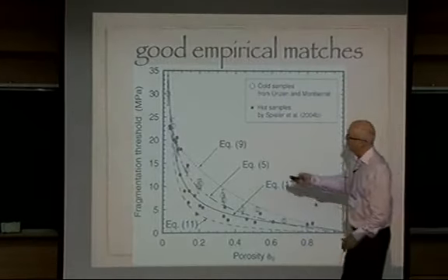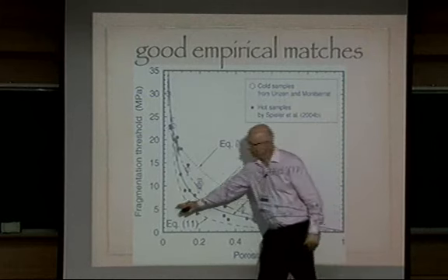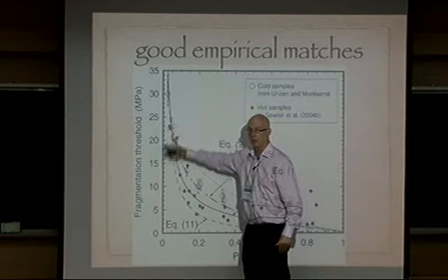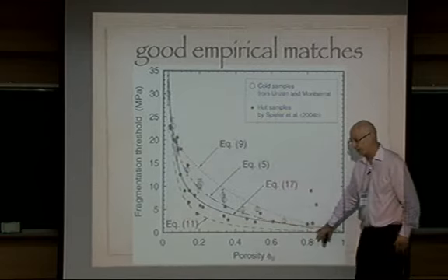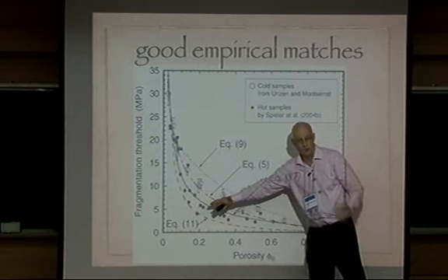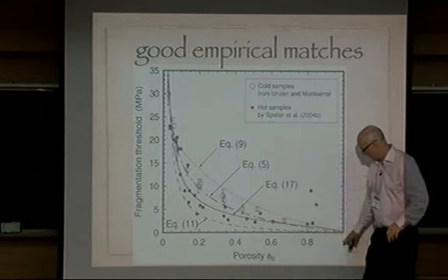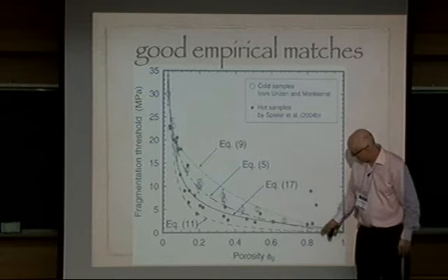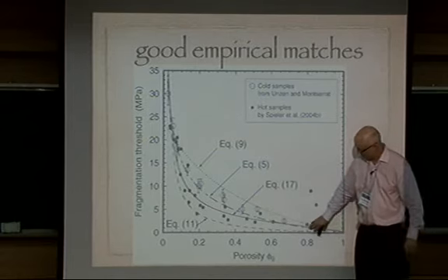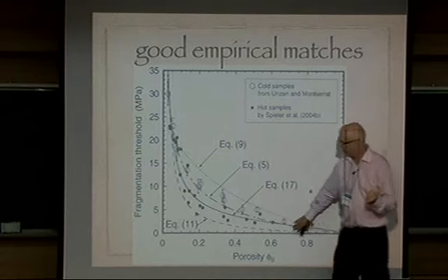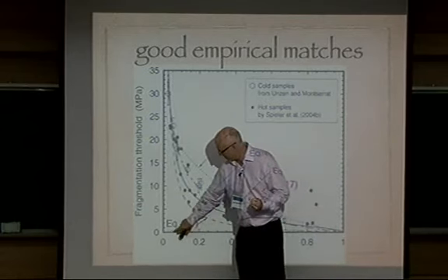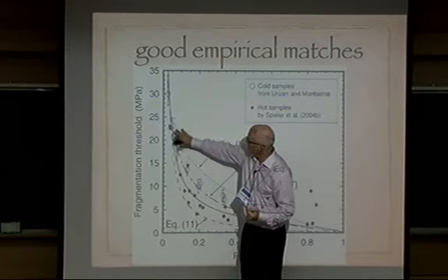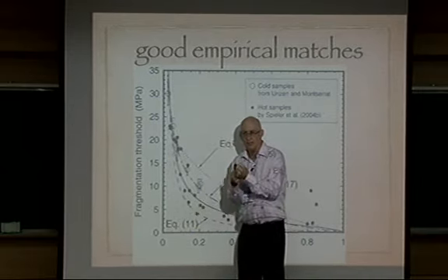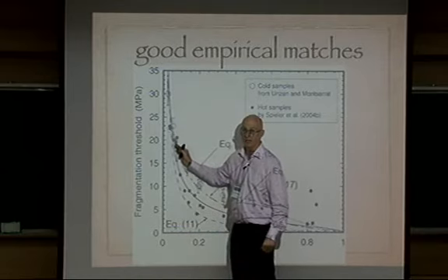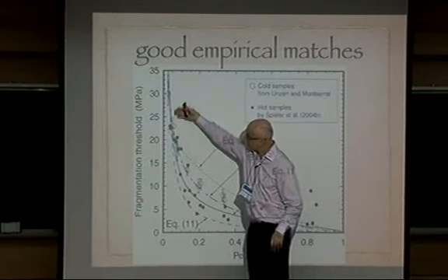They can produce graphs like this one here. The graph is fragmentation threshold: how much pressure do you need to break that rock, versus the porosity of the rock. How porous is the rock? From 0, no gaps, no gas inside it, to 1, nothing but gas. The dots are samples, anything up to 80% holes, right down to less than 10% holes. Of course, the fewer holes you have, the fewer spaces inside the rock, the harder it is to break it. There's hardly any gas in there, so it's hard to get enough gas in to break it.